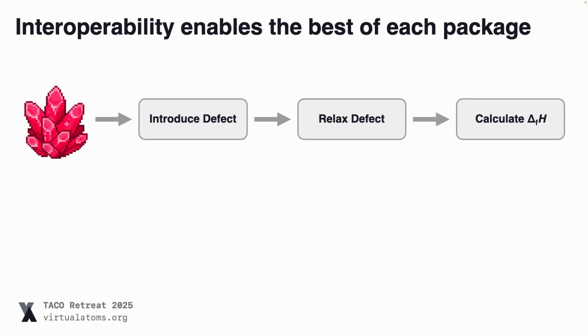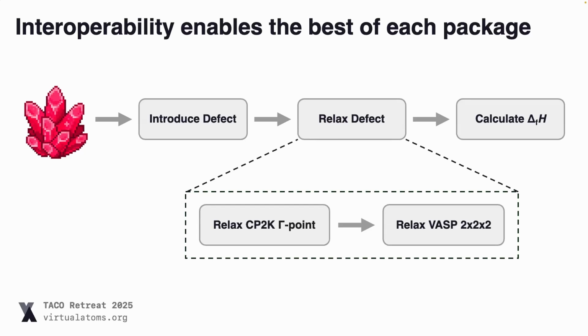What we do in this case is our defect workflow by default includes a CP2K gamma point relaxation, which is very fast, followed by a VASP 222 gamma point relaxation. And actually you don't really have to do anything. The workflow as a whole looks the same. All that changes is this one calculator which calculates the defect formation energy. So it allows us to mix and match DFT packages in order to get the best of what